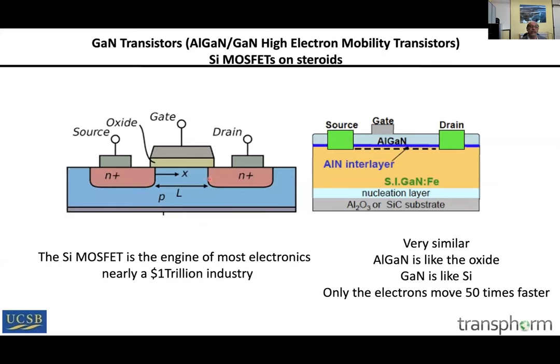This is much like a MOSFET. So here, a MOSFET is a traditional silicon device. Here you can see the oxide here is replaced by AlGaN here. The channel in silicon is replaced by a channel in gallium nitride. What's the big difference? The big difference is the mobility of electrons in silicon dioxide. This mobility is 50. The mobility at the AlGaN-GaN interface is 2000. That is a huge difference. So here you have something that looks like a MOSFET, but it is on steroids, okay?